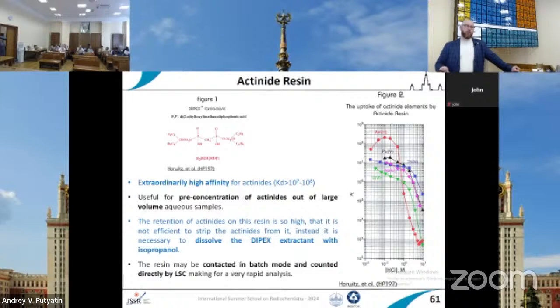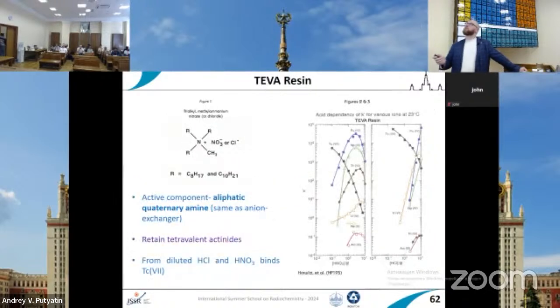Just briefly, the explanation of how different resins work. This is actinide resin, so it contains this complex phosphonic acid, and it has very high affinity, so very high distribution coefficients for all actinides in diluted acidic conditions. So we can use this resin, for example, to make a pre-concentration of actinides from large volumes of liquid acids. Another example is TEVA resin. TEVA means tetravalent actinide resin. So from the name, it is very efficient for separation of tetravalent actinides, so tetravalent thorium, neptunium, plutonium, uranium. But you can see that as far as it contains this amine group, in very low acidic conditions.